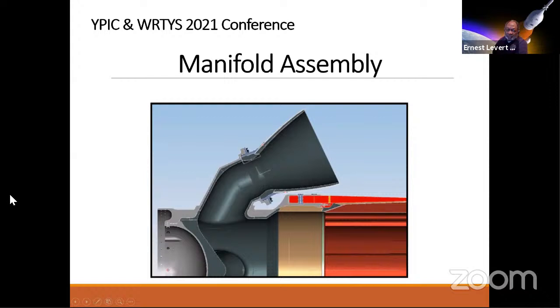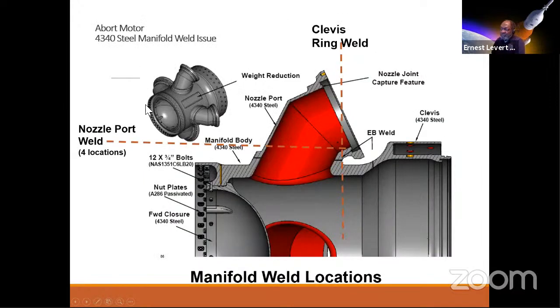And the next slide will show a bit more detail. So you look at the four nozzles and you look at the breakaway here. There's an electron beam weld here. They weld the 4340 together. Then another EB weld that is sitting right here, on this nozzle. The key takeaway from here is the spacing between here. You're trying to do an EB weld in this joint right here, and this is 2 inches thick. 2 inches thick, several millimeters thick here, but it's 4340 material.